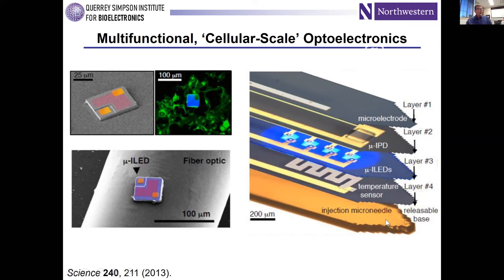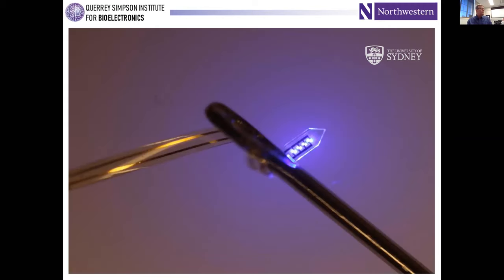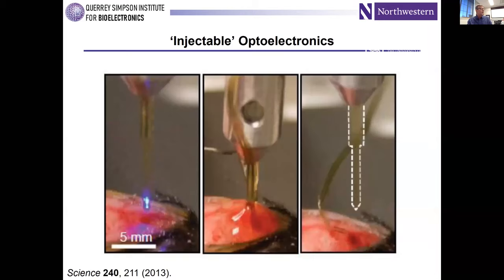And then we bond it with a bioresorbable glue so we can pull out the injection microneedle after we've delivered the device down to the targeted region of the brain of interest. But this is one of these devices for these cellular scale LEDs, very thin filamentary polymer support threaded through the eye of the needle and wrapped around the shaft to give you a sense of the flexibility, what we're talking about. Many orders of magnitude more flexible than an optical fiber. This is what it looks like injected down.